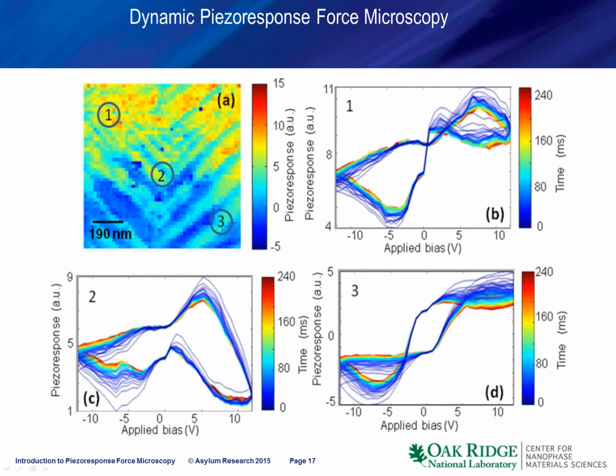In some other regions they do not, and you can see a beautiful example in graph 3, where in the central hysteresis loop there is no relaxation, but in the intermediate loops on the left and on the right, we see a very strong time dispersion of the response. So we actually believe that this behavior is tied to the ferroelectric and ferroelastic switching. The ferroelectric switching for small biases is instant and doesn't lead to relaxation. The ferroelastic switching, which gives rise to the snoozes on the ends of the hysteresis loop, creates a strained structure which tends to relax with time, and we start to see it reflected in the hysteresis loop shape. Again, this and many other applications of multidimensional techniques give rise to very high veracity, very highly reproducible data sets, and they still look for the proper theory in order to explain and quantify them.